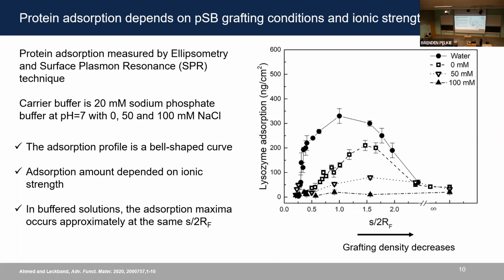So here, the graph on the right is showing the lysozyme adsorption as a function of S/2RF ratio. So as we go from left to right, the grafting density decreases. And we see that the adsorption profile is bell-shaped, and the amount of protein adsorption depends on the ionic strength. So as we increase the salt concentration of the protein solution, the adsorption maxima went down. So this means that in water, which is the poor solvent for the polymers, the coils are shrunken and the protein can penetrate easily through the layer and adsorb on the polymer chain.